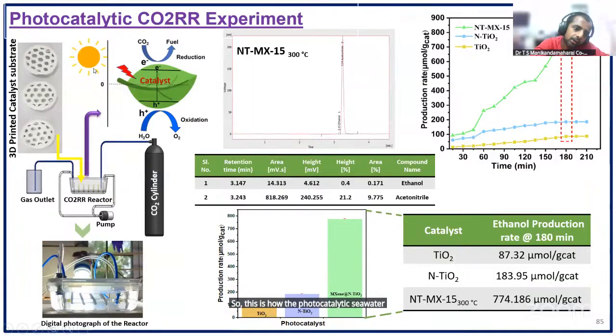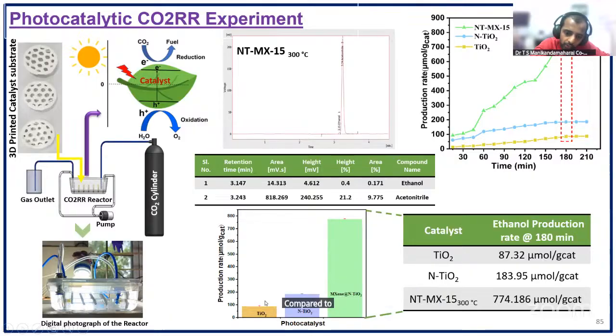So this is how we did the photocatalytic CO2 reactor setup. In the direct sunlight experiment, every 30 minutes we collected the sample for UV-visible analysis. With respect to the production rate, compared to TiO2, the energy band gap is reduced in N-TiO2, so performance is increased. Further, we can add MXene to the N-TiO2, and the production rate increases about 4 times.